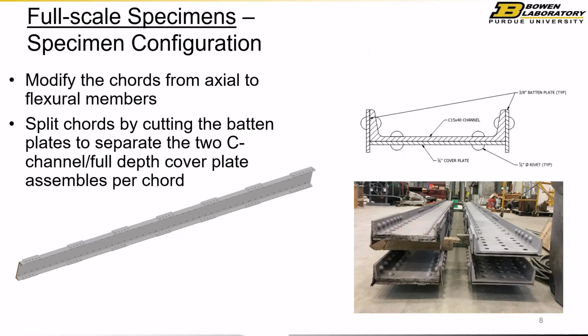And so we split the chord, right, cut the batten material out of it, and then now we have these members. Now you'll notice they're cleaned up, and that had to do with the lead paint. The fabricators couldn't work with the lead paint, but we told them to take care not to remove the pack rust. Now, if you've ever tried to remove pack rust, it's hard to do. So blasting, through a wheel abrader doesn't really take it out. It's like rock, right? It doesn't come out too easy.